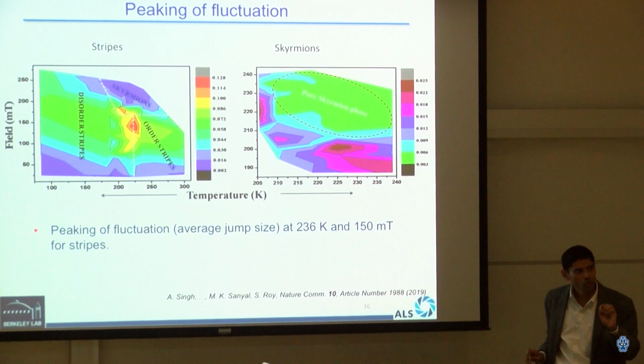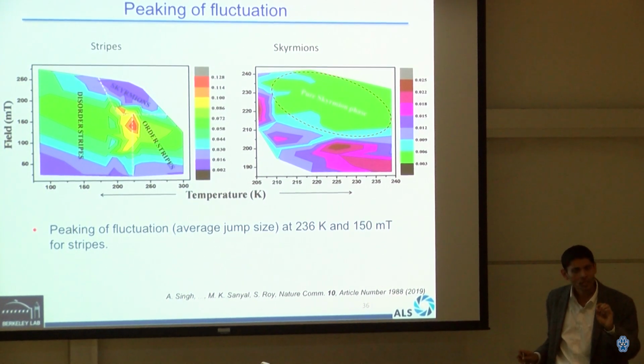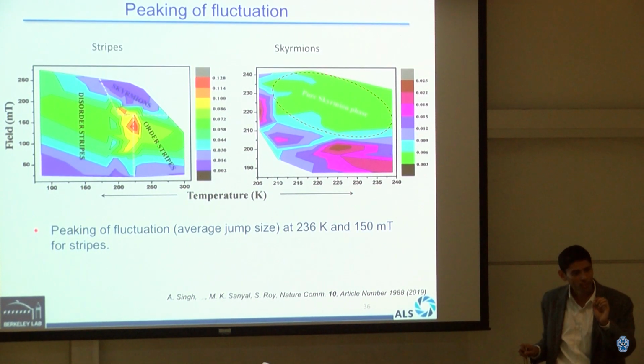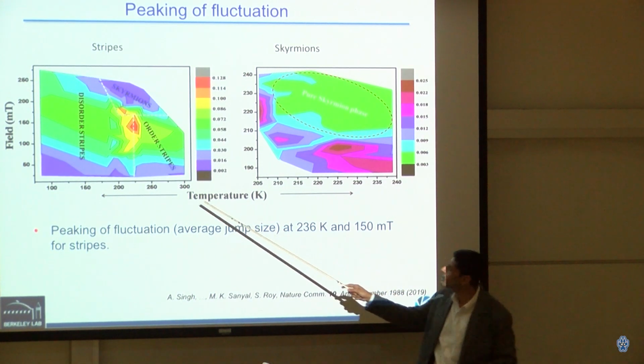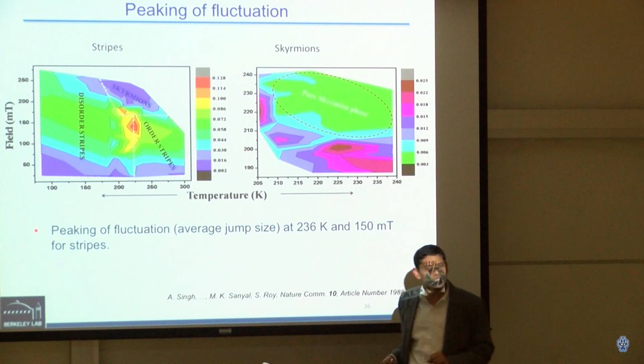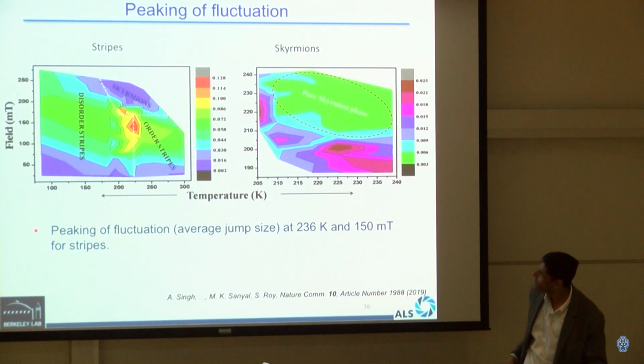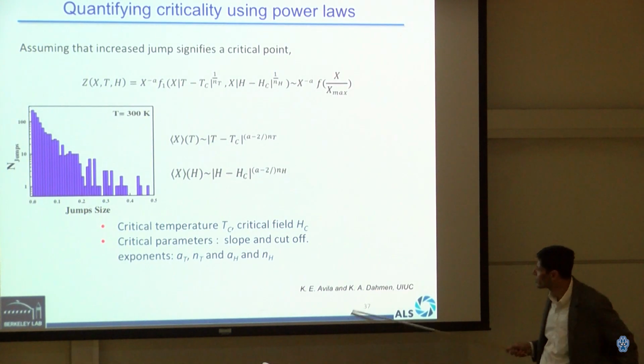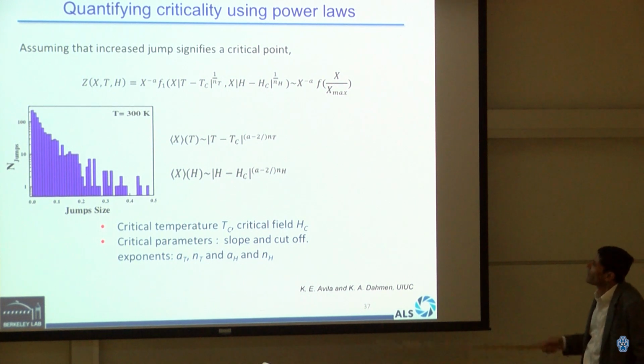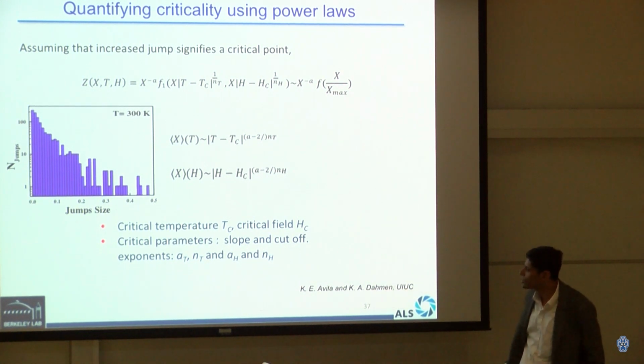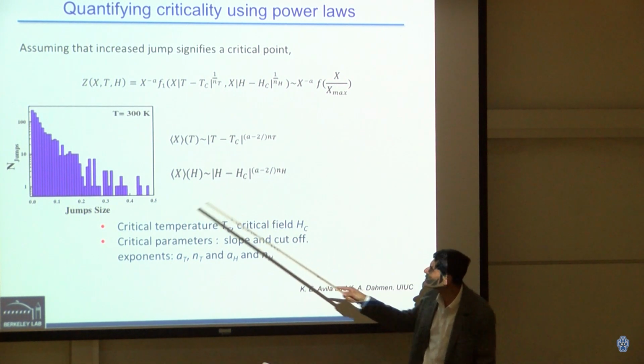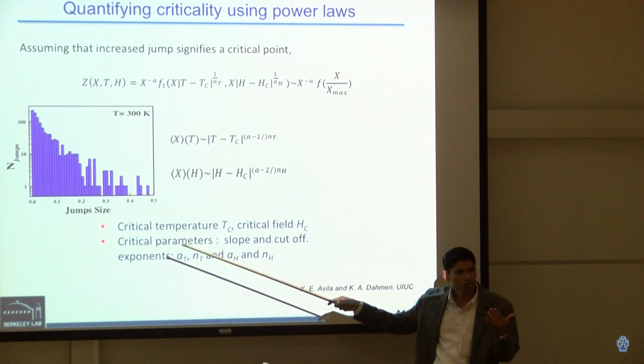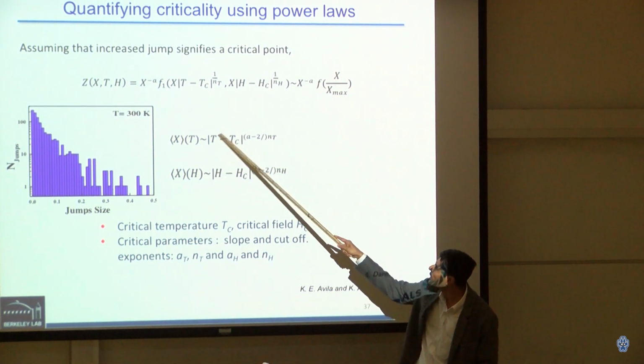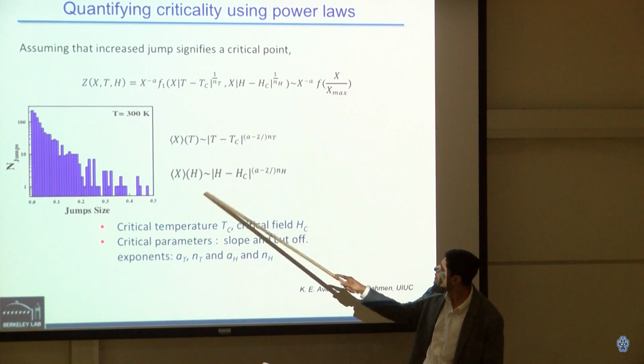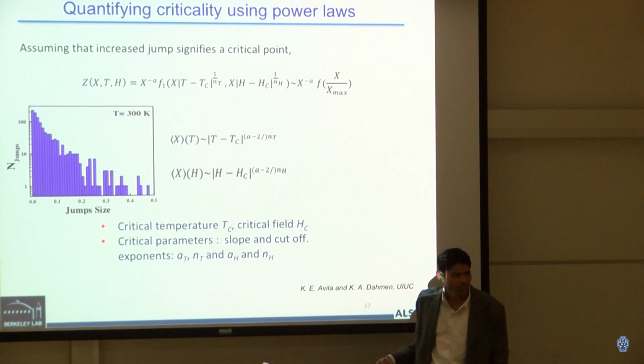When some of you will go and do better physics than me, then you will see that that's an interesting point. It's a critical point and it comes with its own physical properties. So we found out that that little point is indeed a critical point. And then we worked with Karine Dahmen at Urbana, and she gave us this nice theoretical background, and ultimately we can plot out a histogram of those jumps, and they will scale with temperature, with a critical temperature, and scale with field, with a critical field.